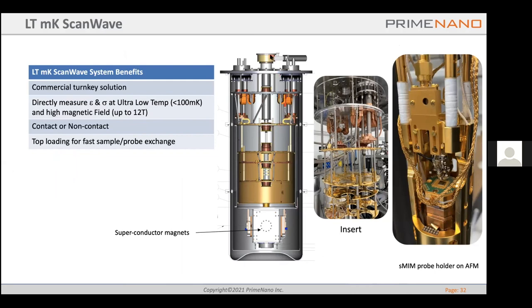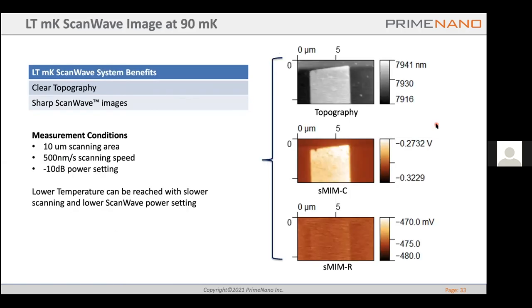And the sample tube, sample probe is inserted in this direction, and AFM and sMIM is set in this position with the superconductor magnets around there. You can see that the sample is sitting here and the probe is sitting here, and the match network is also sitting here. It can reach below 100 millikelvin. And this shows a low temperature sMIM image at 90 millikelvin. On an aluminum dot sample, we get a clear sMIM C image and a clear sMIM R image. The image is pretty sharp, showing that it's very stable and has a high signal to noise ratio.